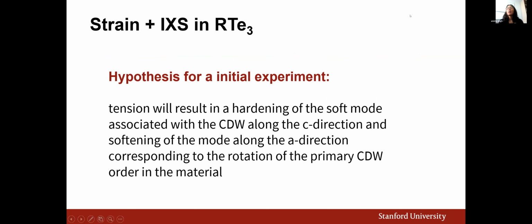All right. So to get started, for an initial experiment, we had a relatively simple hypothesis. If we are still applying tension along the A-axis, and we're looking at the phonon mode at the CDW wave vector along the C direction, we expect to see a hardening of that phonon mode and a softening of that same mode when looking along the A direction, corresponding to this reorientation of the primary CDW wave vector in the material.